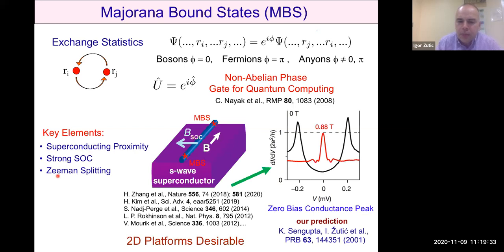Most of the work has been done in semiconductor nanowires, typically III-V nanowires, indium arsenide or indium antimonide, and there would be a direction for effective field due to spin-orbit coupling. There is an applied field, and these Majorana bound states exist at a region that is a little bit like a domain wall. It's between topological and trivial regions. So usually this would be at the end of a nanowire, sketched here. And the signature for these Majorana fermions is often considered to be a quantized zero bias conductance peak.